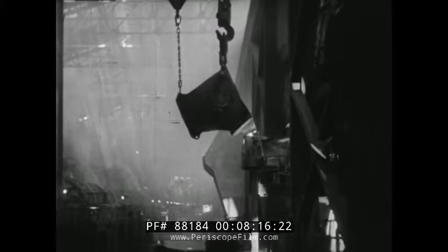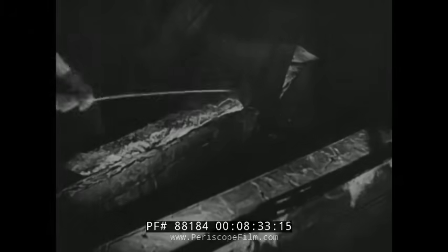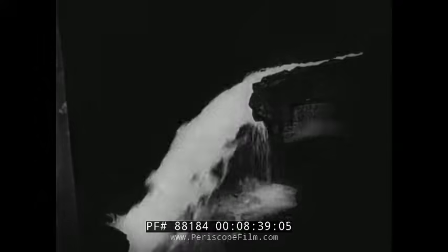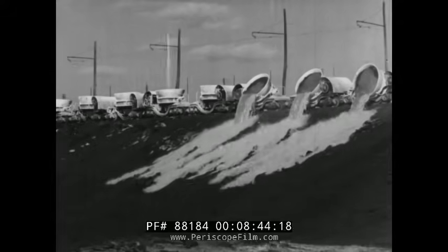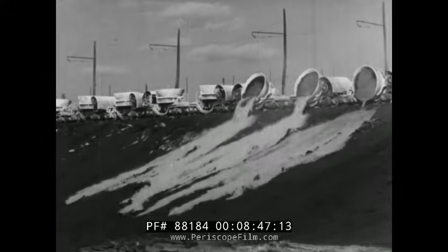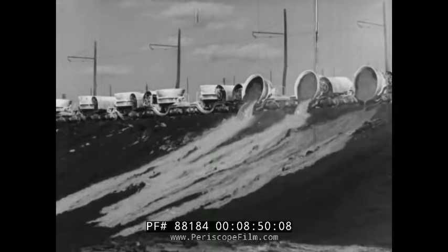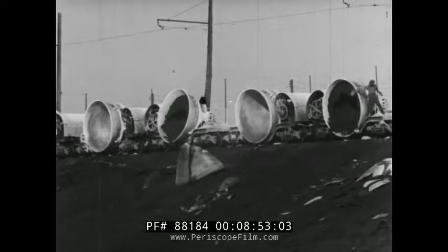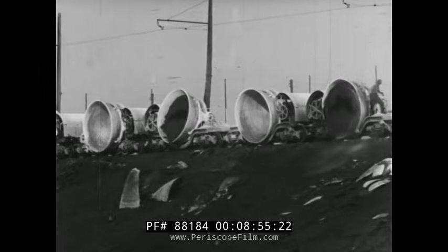The charge in the reverberatory furnace is calcined concentrates. This furnace separates the material into a metal matte and waste slag. The metal matte is drawn off into ladles and then is charged into the converters. The slag from the reverberatory furnaces is tapped into 20-ton pots, hauled out of the smelter and dumped. It is sometimes necessary to loosen the sculls with a dash of water.